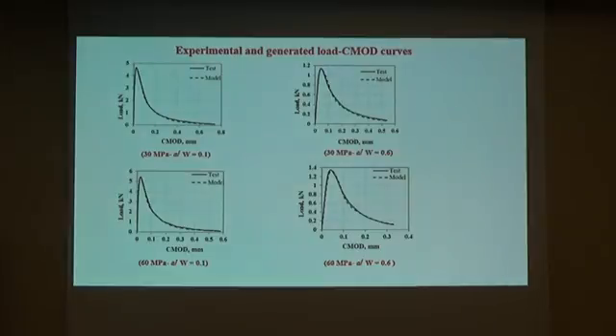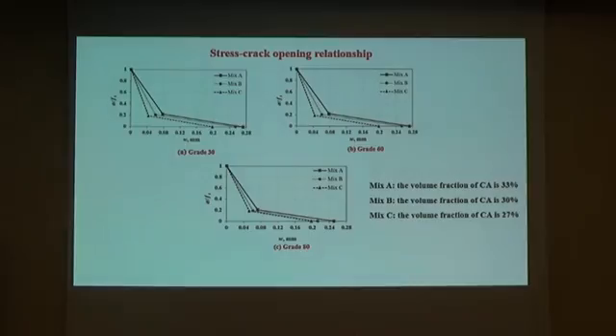Then, as I mentioned before, when using the non-linear hinge model, the expressions of CMOD and the central load are used to minimize the difference between the experimental load-CMOD and the theoretically predicted one. The results of this minimization are shown in these figures here. After that, the parameters of the stress crack opening relationship can be obtained for grades 30, 60, and 80, and it can be seen from all these figures that the crack opening increases with the increasing volume fraction of coarse aggregate.